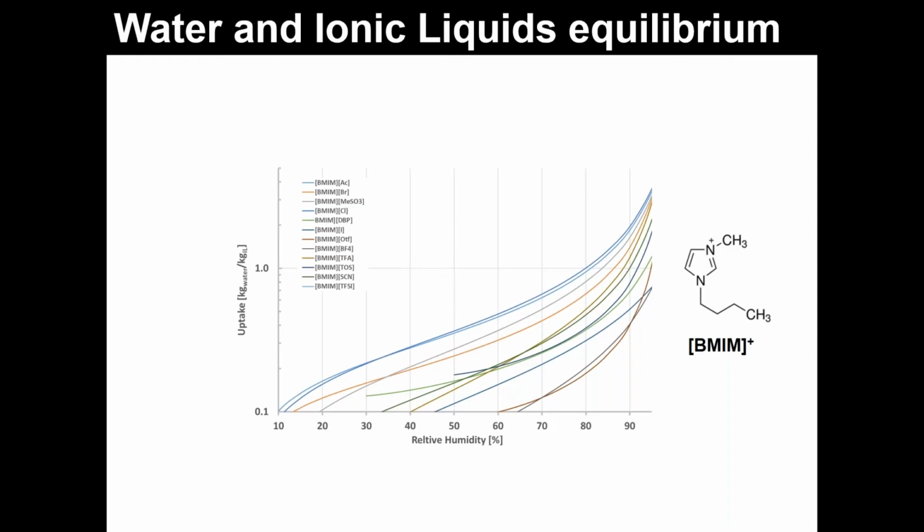Sometimes in our laboratory we switch to the Dubinin-Astakhov just because it is more popular, and it looks easier to use for other research groups. But for a precise fitting, honestly, we should use Guggenheim-Anderson-de Boer, which can fit the type 3 isotherm much better than other types of isotherms.